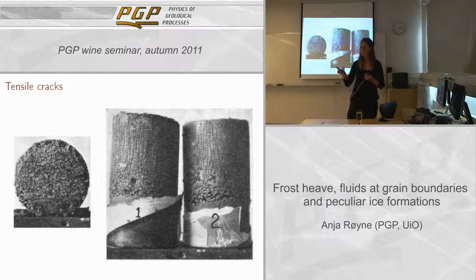And when the ice is below zero, it keeps freezing, and as it draws water from this liquid film into the ice, making the liquid film become thinner, then since this liquid film doesn't want to break, essentially, instead it just draws up more water from below to maintain the liquid film. And then he discussed that maybe the ultimate limit for frost heave would be whether you could actually break this liquid film, and that could maybe be related to